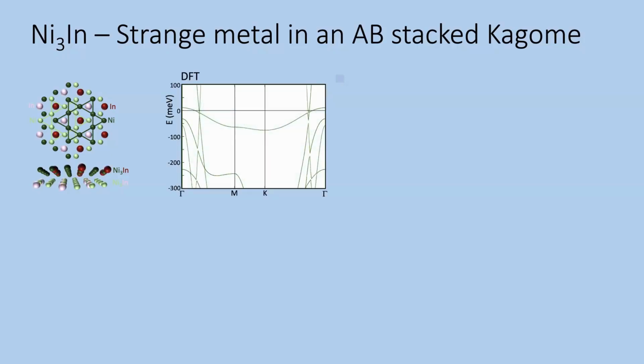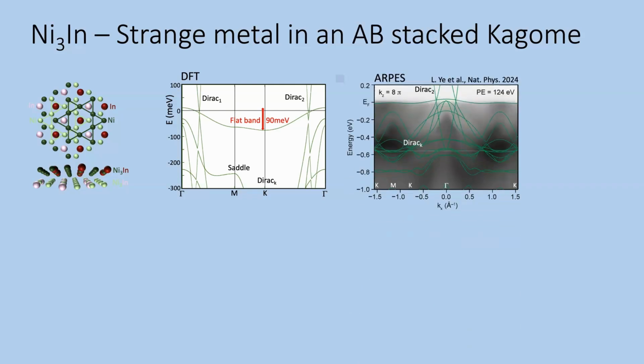And one of the interesting aspects of it, if you calculate its band structure, you find indeed there's a flat band which at neutrality is located very close or at the Fermi level. In DFT, the width of it is about 90 meV. You can identify other kagome-like features in the band structure, like the saddle points at the M point. And in ARPES, maybe the flat band was slightly apparent around the Fermi energy, but they could identify other bands in the band structure, and by fitting them to DFT, they could already see that there's a strong renormalization of the band structure, and the flat band width, which should have been around 90 meV, turns out to be more on the order of 30 meV.